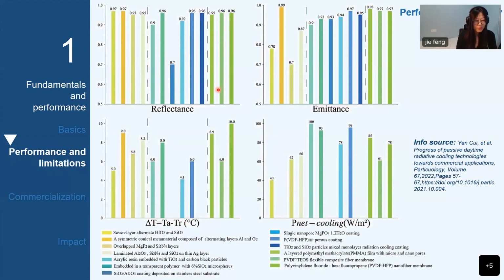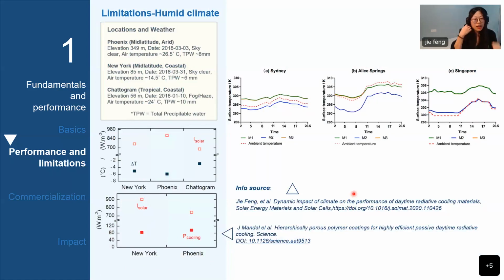Here is a brief summary about the optical properties and cooling performance of some recently reported designs. You can see here we have emittance, reflectance, the subambient temperature, and net cooling power. But please note that the reported performance of coolers cannot be compared directly. Why? Because samples from different papers were tested under different climates and using non-identical experimental settings. Therefore, we just extracted values for your reference. They can't be compared directly. In other words, we need to be objective about the cooling performance reported from various samples from numerous papers.